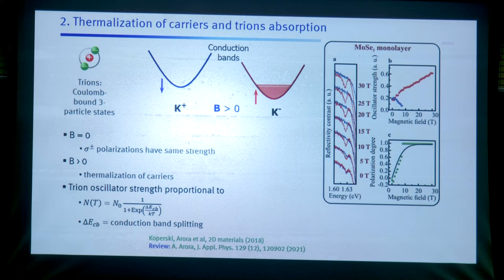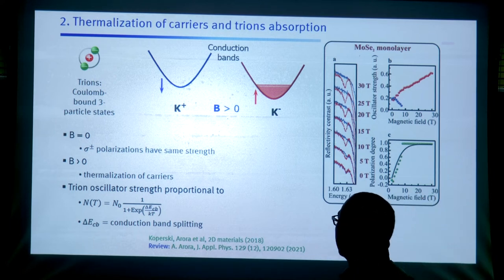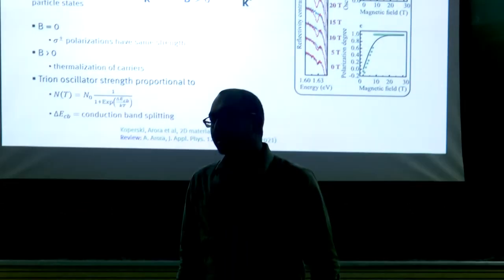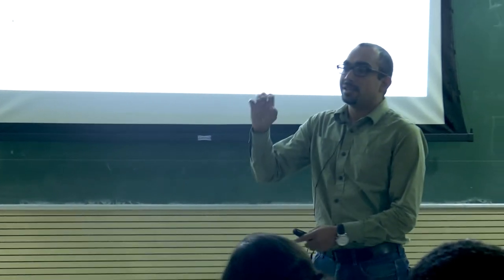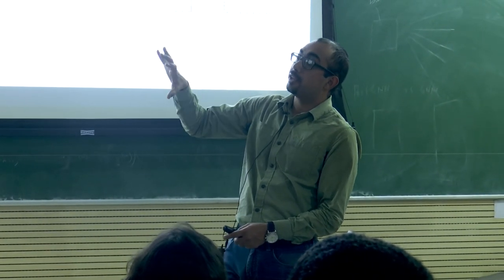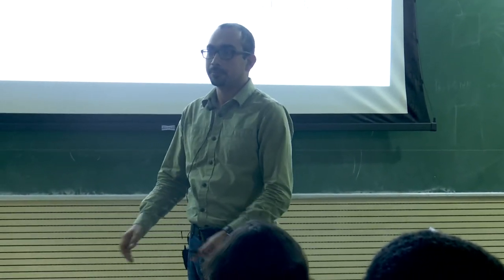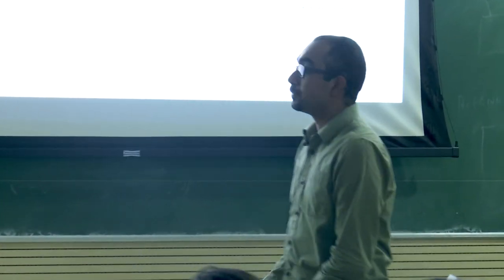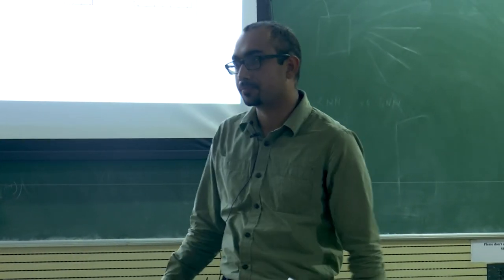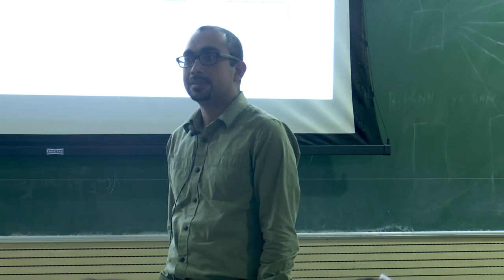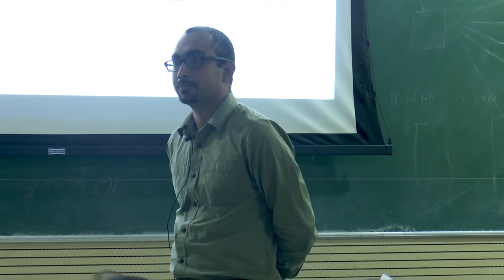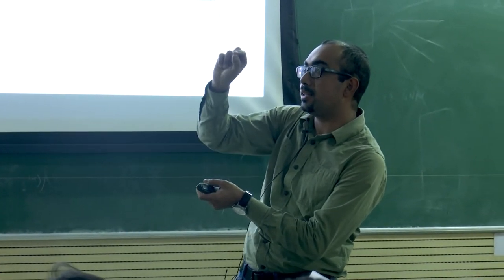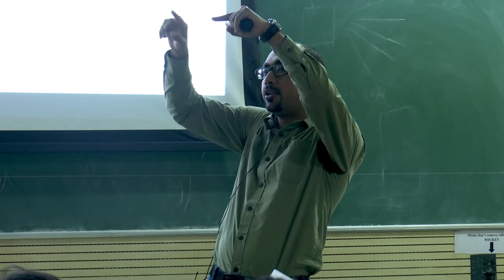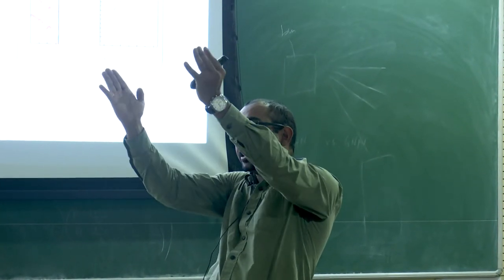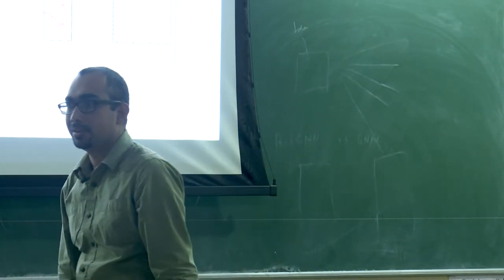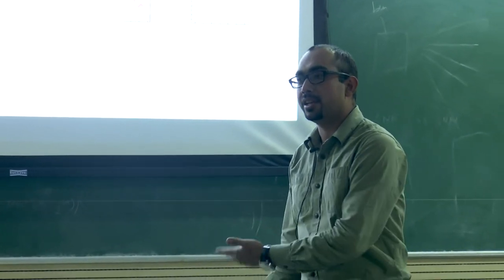But the area is not conserved. Some of the areas might not be conserved because this follows a Fermi-Dirac distribution. That is true. And then there is optical strength. Optical strength depends on how many of the carriers you are actually able to interact with photons. So that goes non-linearly. This is why there is a saturation. Yes, the oscillator strength of these additional carriers is going to be different, because the oscillator strength is maximum at the center of the band. But as you are filling the band, you are making transitions at the corner, outside the light cone, so the oscillator strength reduces there. This is a non-linear thing. We actually checked this in a recent paper in 2020.